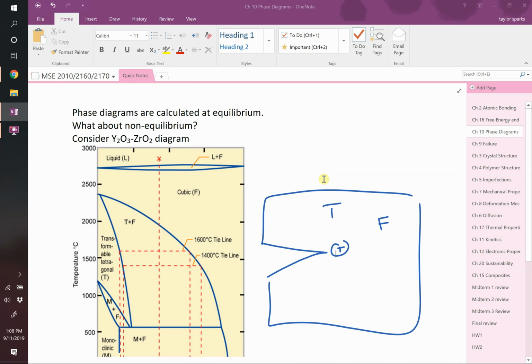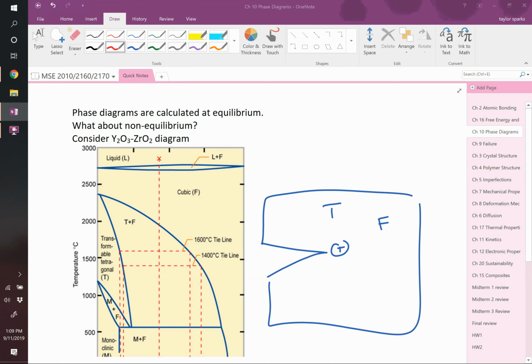So these things have a fracture toughness, which we will learn all about next chapter. Fracture toughness comparable to some crappy metals, which is light years better than most ceramics, right? So this is still brittle. It will still break if you drop it, maybe. But it's a whole lot better than if you made a knife out of, say, pure alumina. Alumina, you can make it equally hard, equally sharp, but if you drop it, it's much more likely to break than this, because this has this transformation toughening mechanism, where again, once it transforms, it's a little bit bigger in that M phase. I have to exaggerate it, but that puts a closing pressure on the crack.